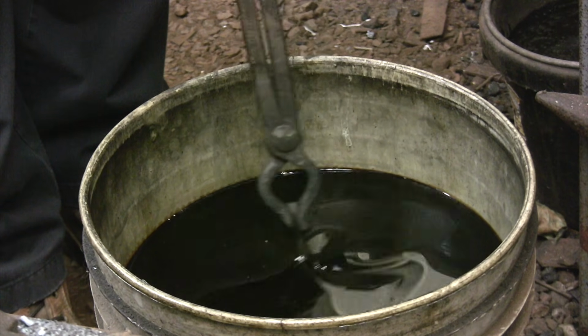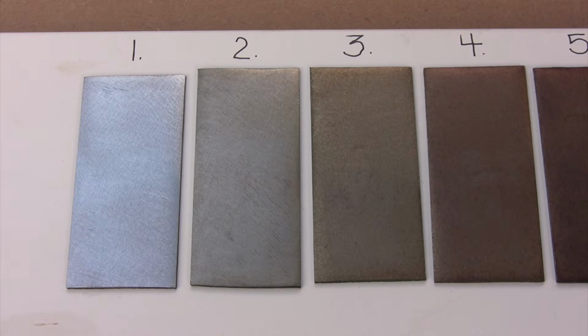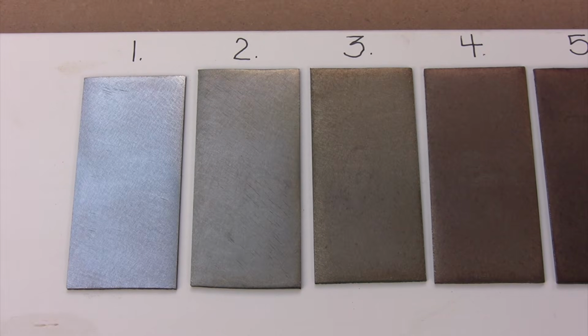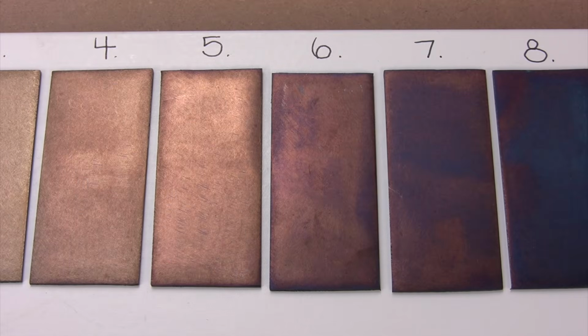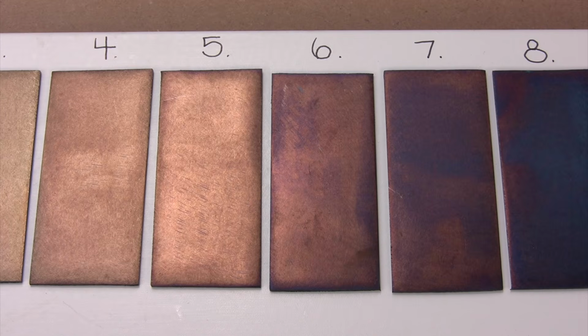we're looking for. The really nice thing about steel is that it changes color as it's heated up. These samples show all of the color changes that happen between the temperatures of roughly 400 degrees to 600 degrees Fahrenheit. For centuries, these colors were the only tool that the smith had for determining the temperature of the metal. They're called oxidation colors, and the only time you see them is on a brightly polished surface.